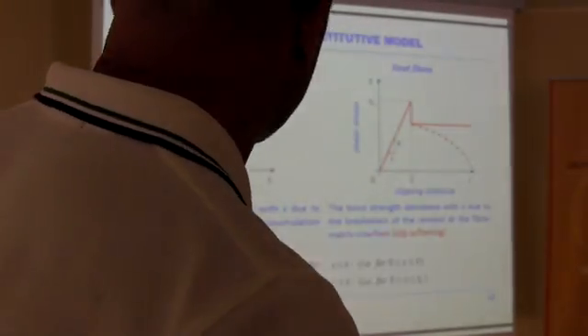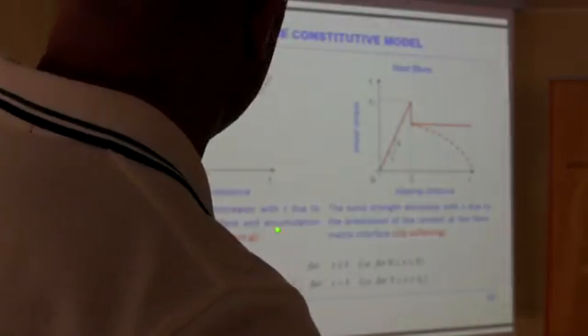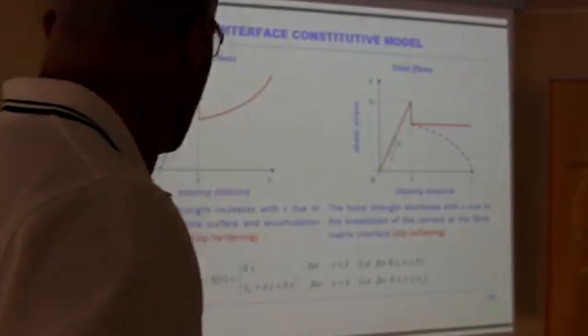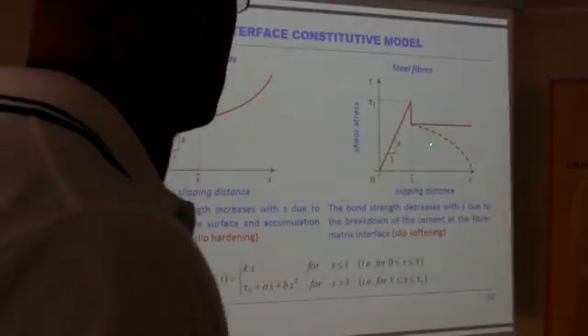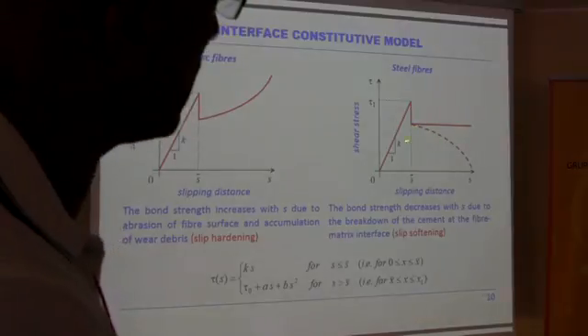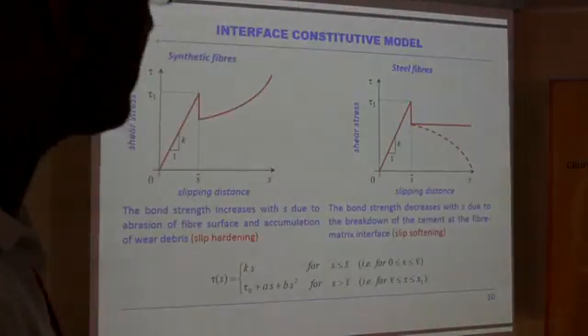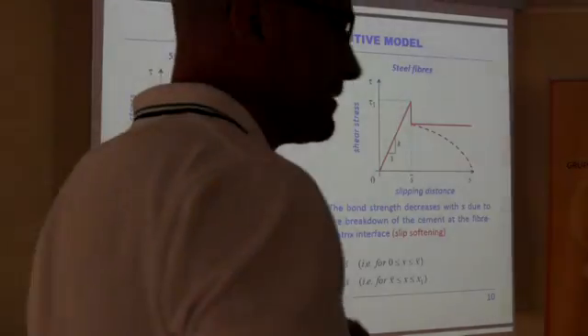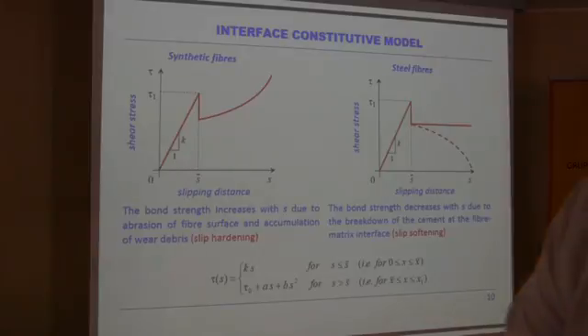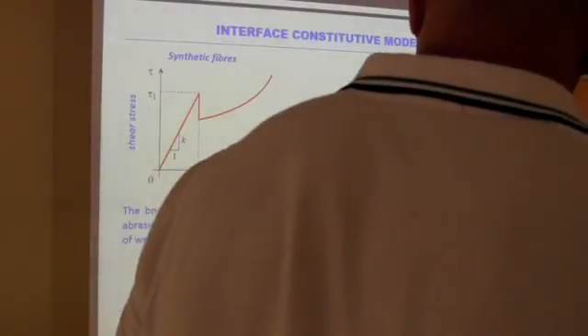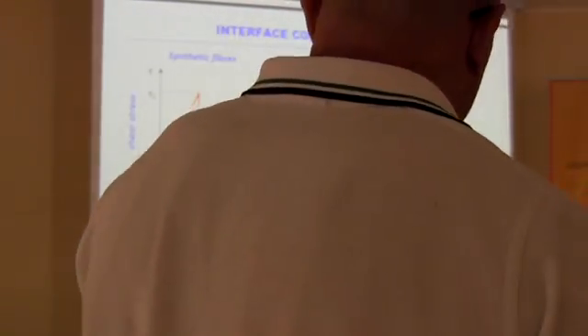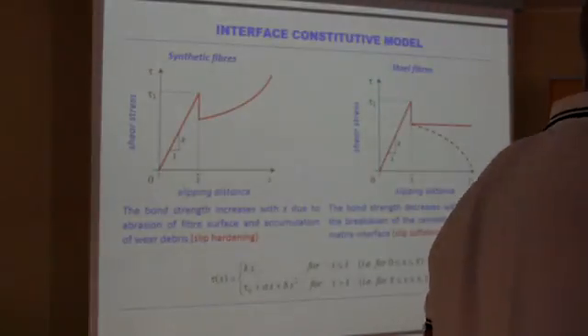Synthetic fibers display a slip hardening behavior in the debonded part due to the abrasion of the fiber surface and accumulation of wear debris. On the contrary, steel fibers display a slip softening behavior or constant frictional stress, and the slip softening is mainly due to the breakdown of cement at the fiber matrix interface. This is the analytical representation for the linear part of the interface constitutive model and the slip hardening or softening part, which is modeled by a simple parabolic quadratic relation between shear stress and slip distance.